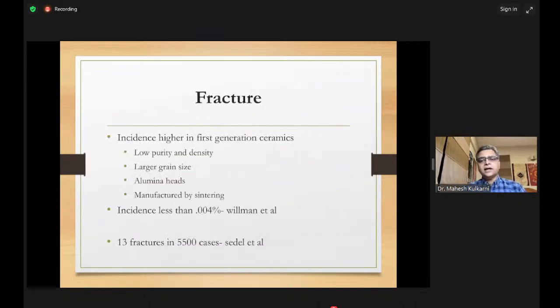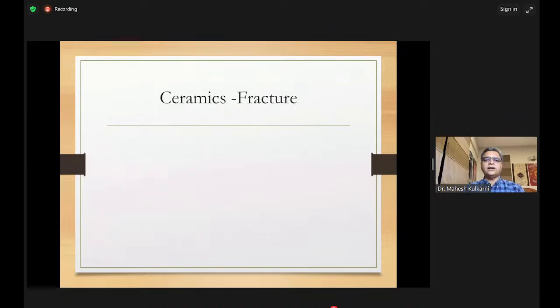So ceramics are excellent. There are two problems with ceramics. So one is fracture. The first generation of ceramics, the alumina ceramics had a problem of fracture. That was because of low purity and density. The grain size of the ceramic was high, and the manufacturing process was by sintering. So even then, the incidence was only 0.004%. If you see Sedel's work, there were only 13 fractures in 5,500 cases.